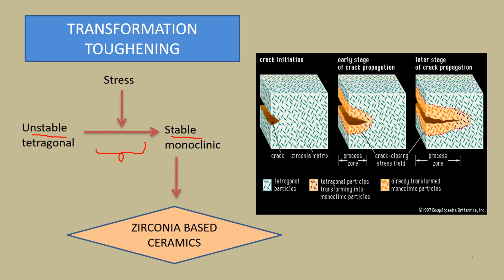In this diagram, we can see a crack which is initiated, and this is all the unstable tetragonal form. This crack will act as the stress inducer. Under the stress, this unstable tetragonal form is going to get converted into the monoclinic form. As already discussed, this monoclinic form, which is 5% larger in volume, will try to compress and prevent its propagation. This addition of zirconia to the porcelain resulted in the formulation of zirconia based ceramics.